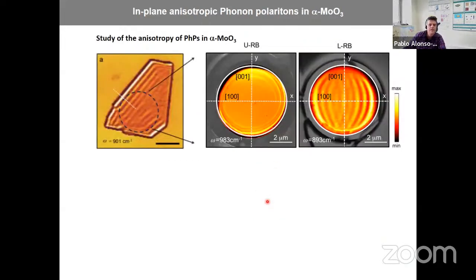To measure this, we thought, okay, we need to probe all directions in the material. And to do that, we decided to make a disk in the material. We did this by focused ion beam. Then we use the tip to excite the polaritons.